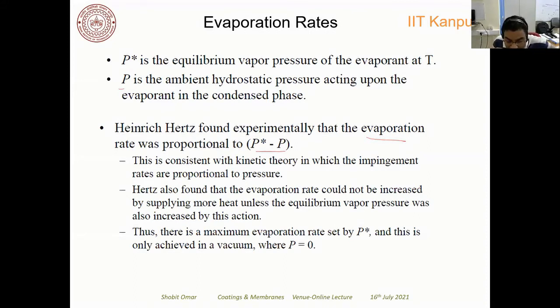Okay, so if you have a solid material and the evaporation is occurring, the evaporation rate is proportional to this P star minus P, and that is also consistent with the kinetic theory, in which the impingement rate is proportional to pressure. Impingement is how much collision is occurring on the surface. So that flux is proportional to the pressure.